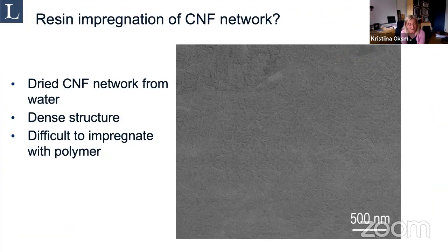But there are some problems. This network dried from water is really dense, and you can see here the same image of the network. We can almost not even see the fibers here, and there are no pores. So it's really difficult to impregnate with the polymer resin, and also the published work on that usually uses solvents to reduce the viscosity of the resin, for example, or then that impregnation is done for a very long time.